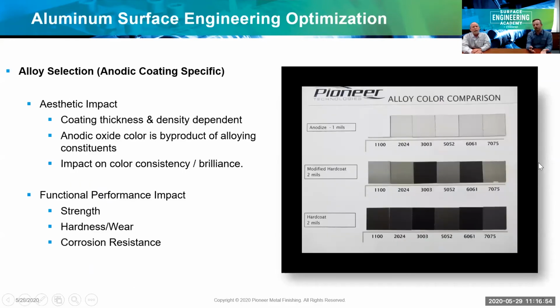Absolutely. So real quick then, a slide to illustrate the oxide layer formed by the different alloy series in anodic coatings. So again, specific to anodic coatings, but important to note here in the oxide coloration itself. Grown from the base metal, the oxide layer itself can have a dramatic impact on the color that you're trying to achieve. If you're dyeing the part, or if you simply want to leave it undyed, know that the oxide layer will produce different impacts. You see that most likely if you're using 7000 series, as the thickness increases of an anodic layer, a greenish effect will emerge, and that's really the zinc coming out in the alloying constituents.